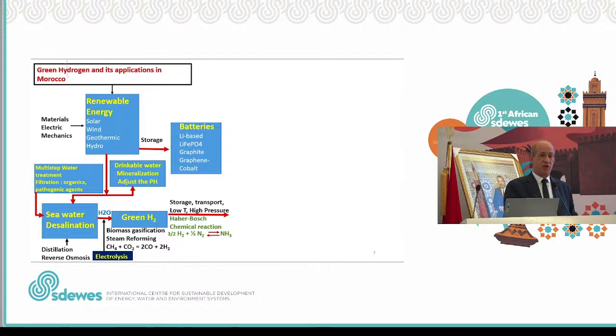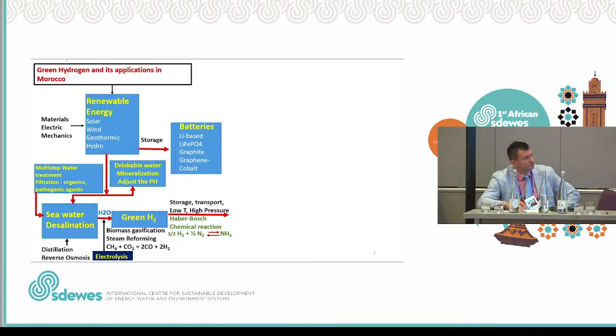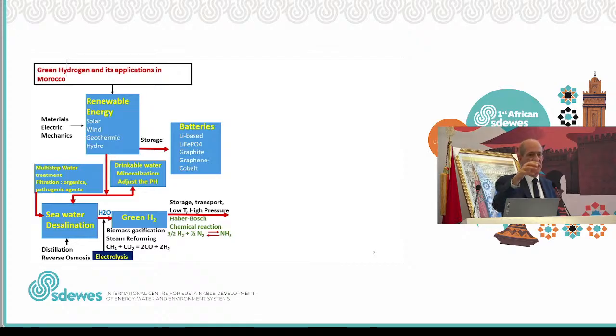High pressure, when you say high pressure, is more than 300 to 700 bars, which is huge. Or you can transport hydrogen through chemical reaction. Because if you use hydrogen plus nitrogen that you can capture from the air, then you can obtain ammonia. Yet you need some catalyst, but this reaction is an equilibrium chemical reaction. So you can go from hydrogen, you generate ammonia, and once you have ammonia, which is liquid, then you can reverse the chemical reaction to obtain hydrogen. So this is what Morocco is doing.